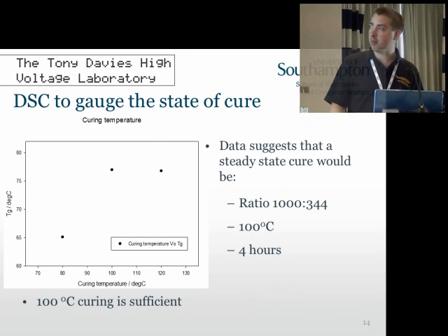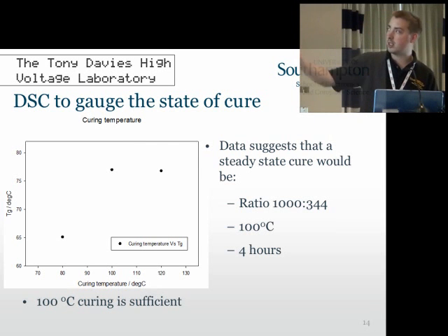Again, doing the same with the curing temperature, has shown that 100 degrees is the minimum to make sure that we have a steady state of cure, which has given us these conditions for epoxy.